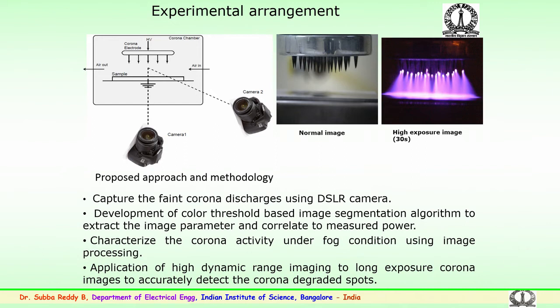For that, we tried to use DSLR cameras, placed at different angles as shown here. The information was captured and a method has been formulated. Initially, to capture the faint corona discharges, these DSLR cameras were used with decided camera settings and capture time. Then a color thresholding based image segmentation algorithm was developed, particularly to extract the image parameters and try to correlate them to the measured power, that is the power which we have measured in the laboratory. This image technique was used to see how the correlation could be carried out, and with the thought of characterizing the corona activity, particularly the activity under both mist and fog condition using image